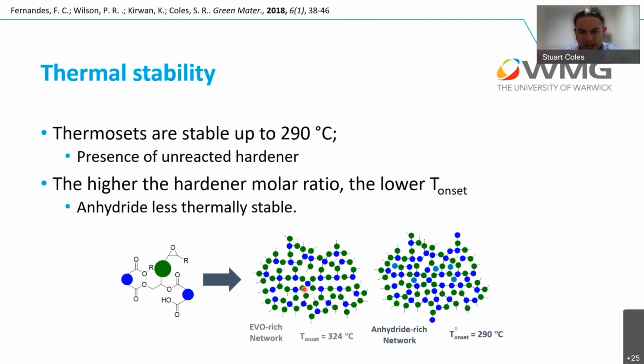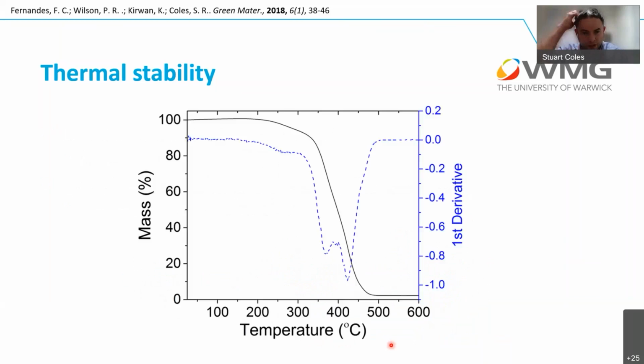But we effectively have a vegetable oil rich network that had a T onset of about 324 degrees C. An anhydride rich network would give us an onset temperature of about 290. This can be envisaged here. You can start to see that drop with effectively the hardener event first, and you can see the difference between the two derivatives.